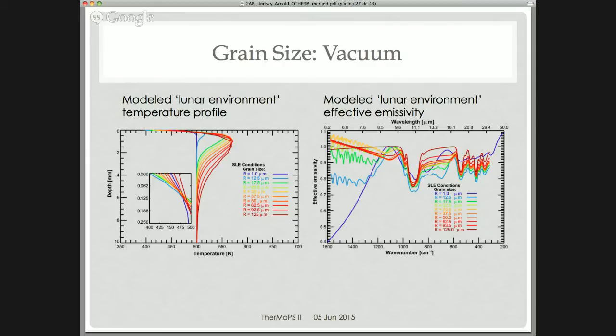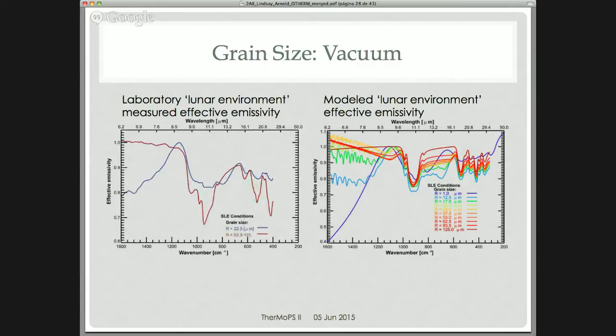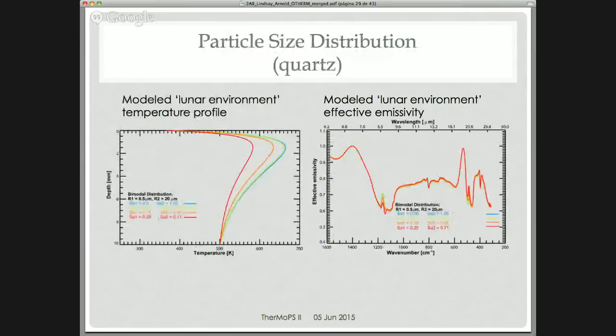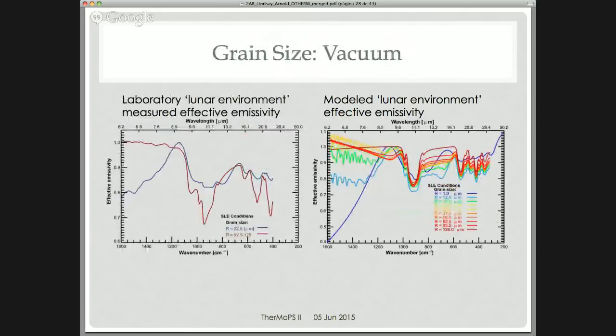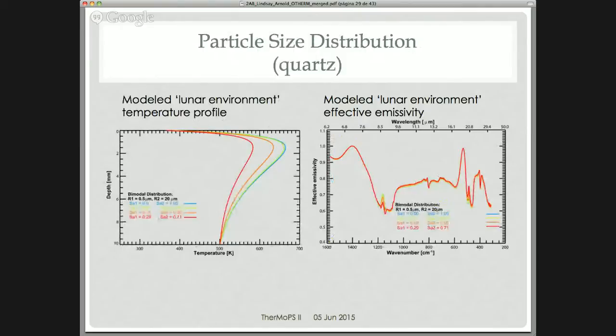Okay. And then finally, I noticed that our less than 22 micron spectra looks like the much, much smaller stuff we modeled, like the 1 to 10 micron stuff. So I wanted to see the effect of particle size distributions that have different ratios of very fine particles to a distribution centered around 20 microns. This is based on the plot that Neil showed earlier of the aerosize data of quartz. So I have a distribution centered around 20 microns, a distribution centered around 0.5, and I varied the ratio of the relative surface areas from 0 to 0.3 for the 0.5 microns. And what's odd to me is that this doesn't seem to change things too much.